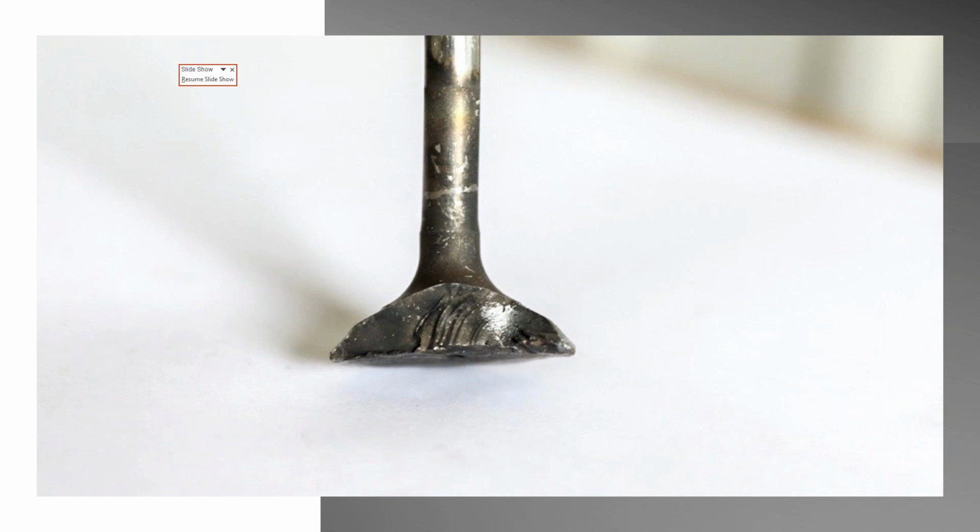And they started changing glow plugs. It didn't take them very long into investigating to find that the valves are actually splitting. And they're splitting because inferior material was used, but also keep in mind that they changed an aftertreatment system that used to be more along the lines of the 6.4. We were using a DPF system, true enough, but it was through the 7th and 8th cylinder on the exhaust stroke that we were introducing the catalyst for the burn, to lower our emissions.